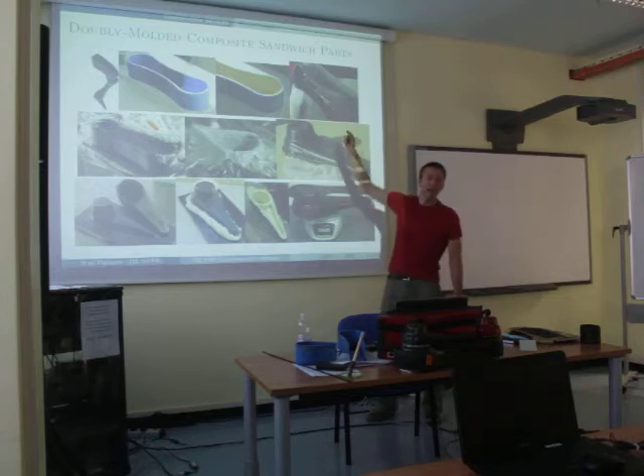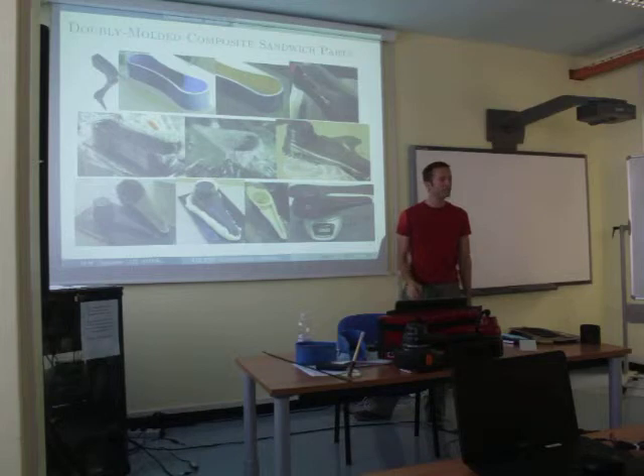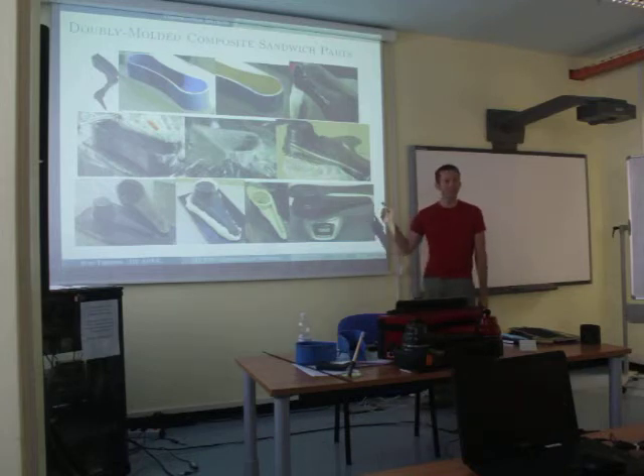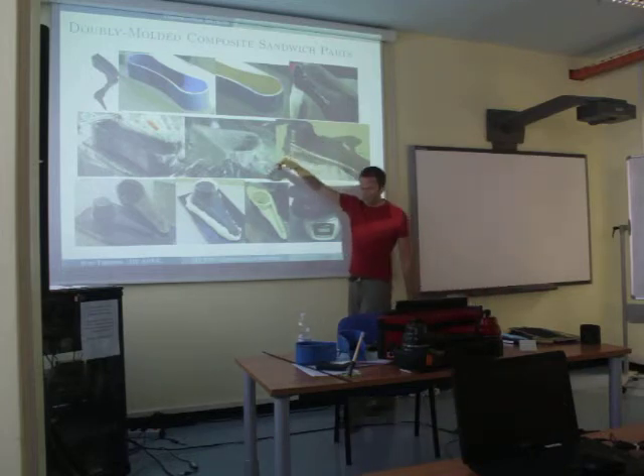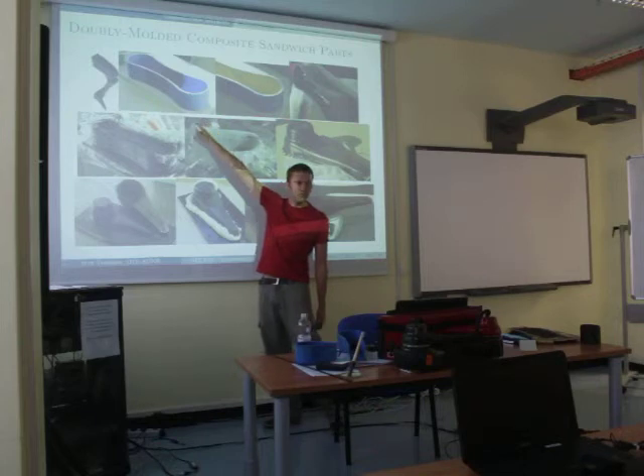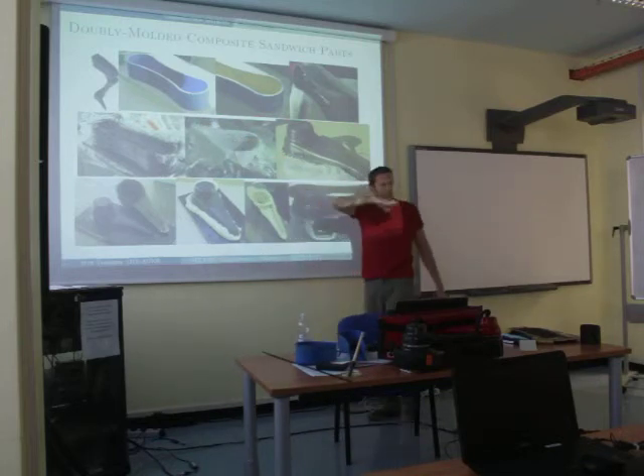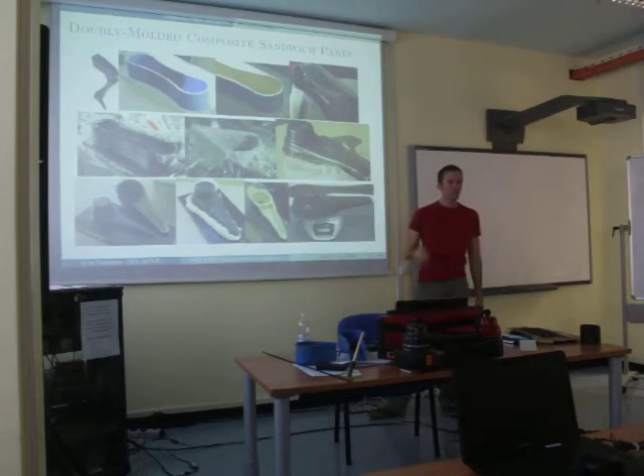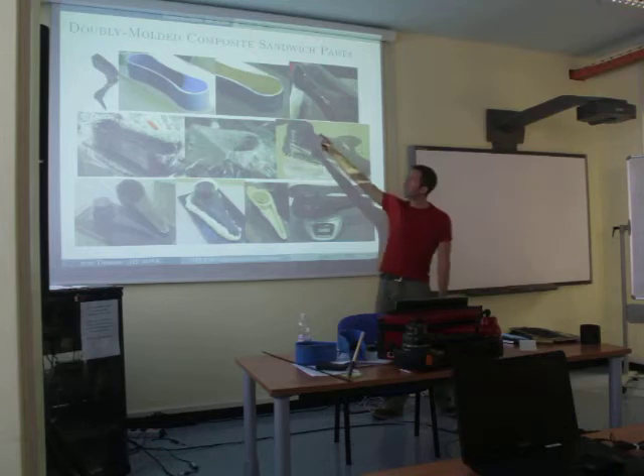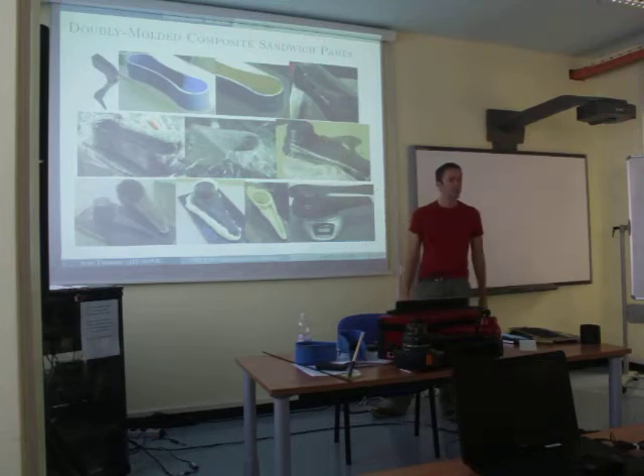I then painted it black with gloss black. Glossy black shows all your mistakes more easily than a white color. Glossy black lets you realize how many mistakes you made doing this. The reason I added the Bondo was because the surface you get straight out of the printer has lots of little irregularities, and I needed something to fill in those little gaps more smoothly. You end up with a stair-step effect. So I filled it in with the resin and then just sanded it lightly. It took a couple hours.